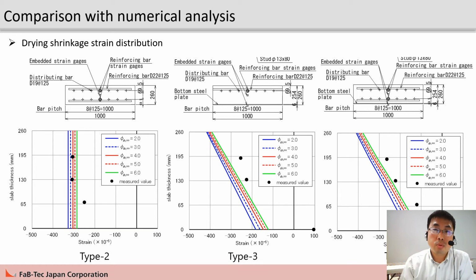In type 3 and type 4, the difference between the analysis and the test results clearly increases upon approaching the bottom steel plate. In particular, the bottom steel plate in the test shows tensile strain compared with compressive strain in the analysis. It's hard for water in the concrete to dissipate because the bottom surface is covered by the bottom steel plate. Thus, the drying shrinkage value on the bottom of the specimen is smaller than that on the top.